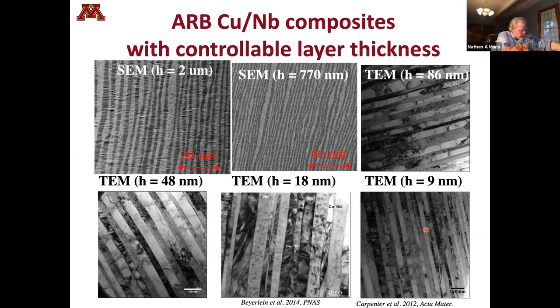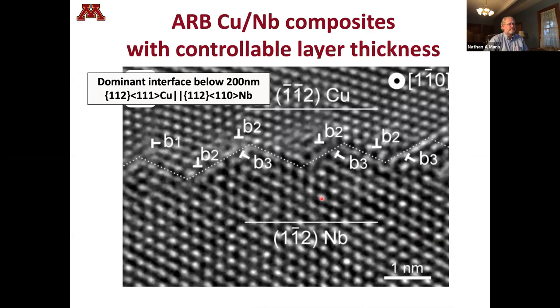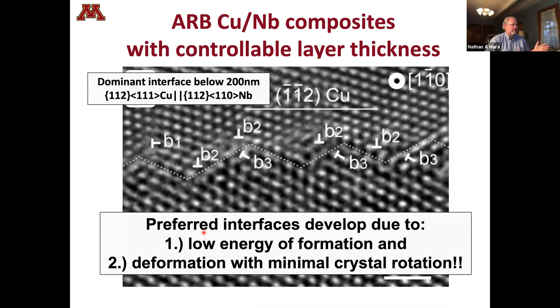And so these layers end up having a very uniform kind of structure between the layers. This is what I've shown before with this zigzag structure. About 75 or 80% of the interfaces resemble exactly what I'm showing here on the screen. This becomes a wonderful model system in terms of being able to say, here's a specific interface structure and here's how it deforms. I won't get into the big story here about how these form; there's a long, long story behind that. But they develop because they have a low energy of formation. So thermodynamically, they want to be there in the microstructure. And they can deform to large strains with the crystals minimally rotating, so everything stays pretty static.